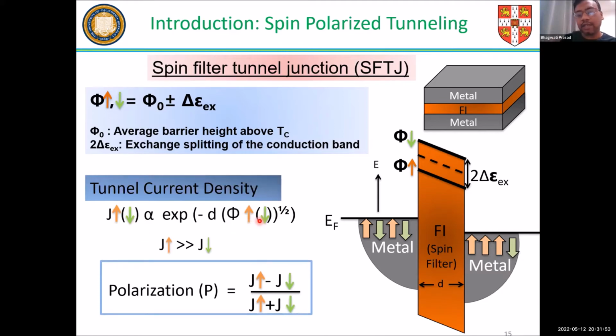So if you have two different barrier heights for two different spin directions of the electron, then you will see that the current on this side would be mostly having the spin orientation of the barrier height which is lower. So basically that way you can generate a highly spin polarized current. Even if you have a small separation between the barrier heights for these two, you can see a large difference here because it's exponentially dependent.